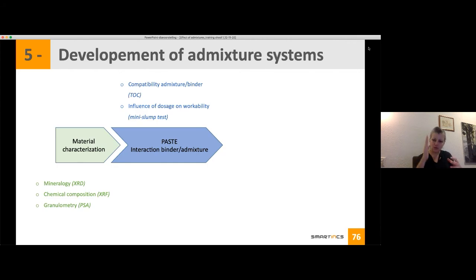This is where you have your saturation dosage. If you go above this dosage, it won't help anymore with the workability and the stability of your concrete. So between these two points, the critical and saturation dosage, is where the dosage of your admixture is. And depending on the workability you want, you can choose your dosage.